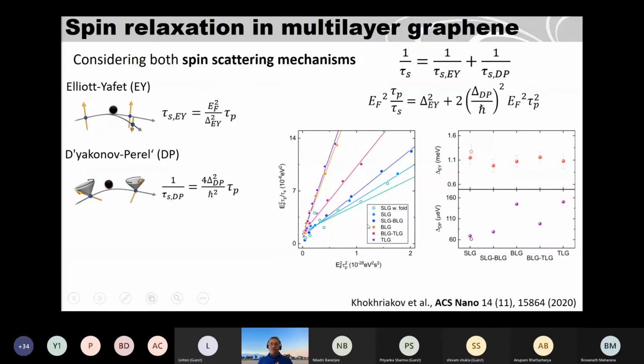And to understand the mechanism for spin transport in graphene, I showed you last time the Elliott-Yafet mechanism and the D'yakonov-Perel mechanism. The Elliott-Yafet mechanism is directly proportional to the momentum relaxation time. But the D'yakonov-Perel is inversely proportional to the momentum relaxation time, because it mostly depends on the spin-orbit coupling, like from the inversion symmetry of the system. We don't know which component is dominant, so we can take both of them together. This is the spin lifetime in total, taking the Elliott-Yafet and D'yakonov-Perel both together. If we put these numbers here and solve this equation, we find a simplified equation for how the momentum relaxation time depends on the spin relaxation time. So you can just plot this as shown here.